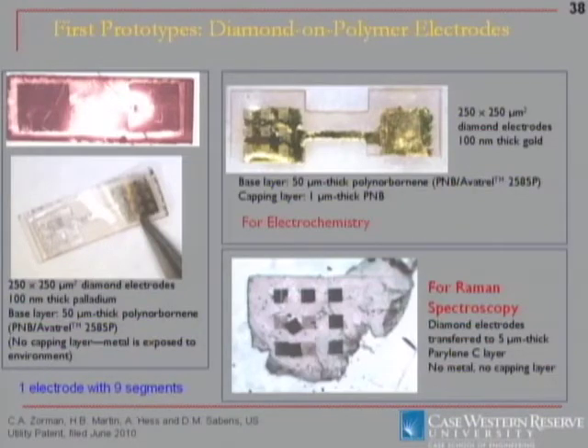This one was not insulated, so we could not use it as an electrode. The palladium was still exposed, but it showed that we could transfer the diamond, and I'll show you what we actually do in a moment. This was a gold contact here on the right-hand side, where we actually insulated the gold. And we had to watch how this was sliced in order not to expose the gold for electrochemistry. The polymer we're using is polynorbornene. This actually fluoresces quite a bit. We wanted to analyze our diamond with Raman spectroscopy. We had to switch polymers in order to be able to see it in the Raman, and that is just an example. It doesn't seem to adhere as well in the Parylene.